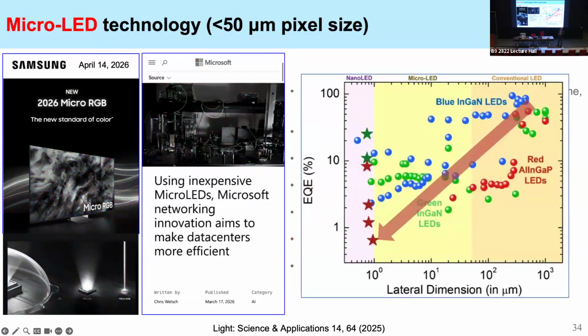However, one of the Achilles heels of micro LED is that once you reduce the size of the LED from, let's say, 1,000 micrometers to hundreds of micrometers down to tens of micrometers, there is a significant reduction in the so-called EQE, the external quantum efficiency of the micro LEDs. This becomes a severe problem, because you don't want to lose efficiency. The blue LED we use for lighting today has an efficiency close to 100%, meaning that most of the electrons and holes we inject from the grid into the LED become photons. But in this case, many micro LEDs actually operate at about 10%, so you lose a lot of photons into phonons, which are heat.